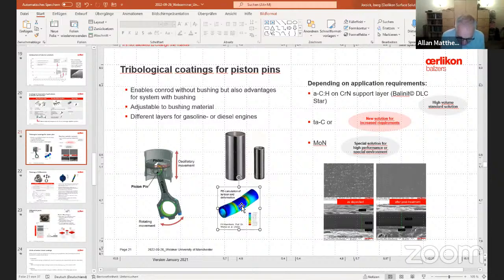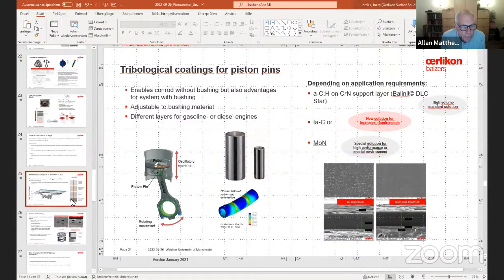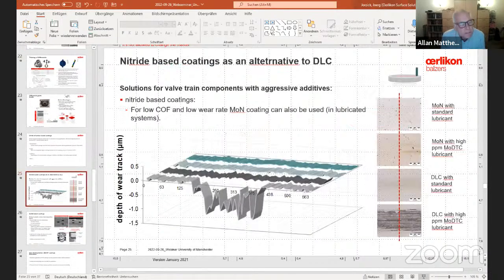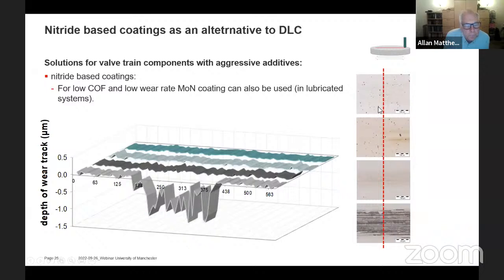My final question was about your lubricant tests with the nitride coatings. Yes. Were both of those surfaces coated? We only coated this disc. The pin was uncoated. Right. Yeah. So it was a classical 100 chromium 6 ball that is usually used for this kind of wear tests, and only the disc here was coated.